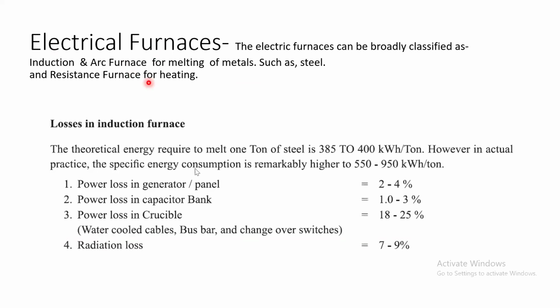So for steel melting, arc furnace is used. Now the losses in induction furnace: the theoretical energy required to melt 1 ton of steel is around 400 kWh per ton. If you visit steel plants nowadays, every steel plant normally declares the amount of electrical energy required per ton of their scrap melting. In many cases I have read 420 kWh per ton or 430 kWh per ton, in some cases around 390 kWh per ton. So this is how the theoretical energy required to melt 1 ton of steel is in this range. And this consumption indicates the specific energy consumption of melting steel, and many steel industries are trying to achieve these norms and stay near or close to 385 kWh per ton.